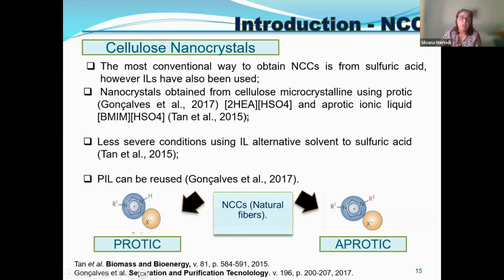We obtained nanocrystals in a previous work with 2-hydroxyethylamine, and also we used imidazolium. So we used protic and aprotic ionic liquids. You can say they are of different nature, but what we have in the literature was the butylimidazolium hydrogen sulfate. Maybe I can use that for comparison, but we use more ethylammoniums and ammoniums in general in our lab, so we chose this one. They have less severe conditions compared with sulfuric acid, and most important, we proved that the ionic liquid could be reused, protic and aprotic. We can process and afterwards reuse the liquor more than one time.